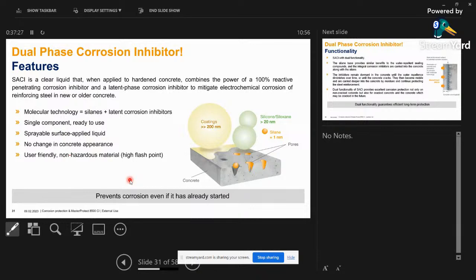In terms of its features, it is a clear liquid, just like water. And if you look at a typical size of a coating, it is 200 nanometers. And if you see silicones, siloxane, it is much higher. And if you see the silane, it is much smaller. So therefore, the penetration of the silanes is much deeper in concrete compared to all the other impregnators which are available. It can be spray applied.